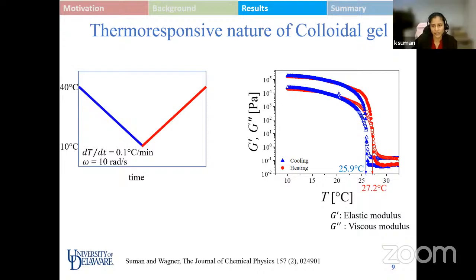Yeah, and this can be eliminated or reduced by doing more and more slower steps, or equilibrating it more at a specific temperature, and then we can decrease this temperature gap. So if we do it at a very fast temperature ramp rate, the difference of the hysteresis is going to be more pronounced as compared to when we do it in a very slow and equilibrated step. It's going to be quite less. So it can be minimized using equilibration in time and temperature.